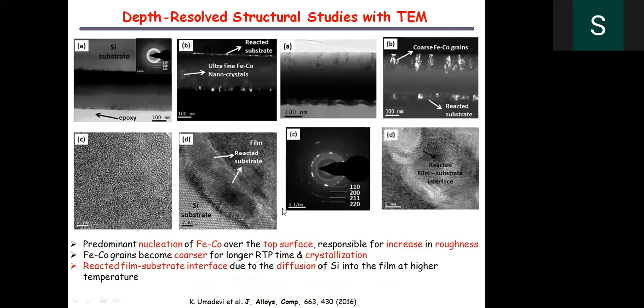In these films, to understand this one, we have also done depth resolved electron microscopy studies. When we heat treated this material, we found ultra fine nanocrystals of FeCo precipitates. As we do a rapid thermal annealing, we also observed that the film substrate interface becomes very rough. You see there is a reaction happening at the film substrate interface. If you want to see more clearly, the high resolution TEM image shows there is a diffusion of this material into silicon. The silicon interface is becoming very bad, and as we increase the temperature, it becomes much worse.